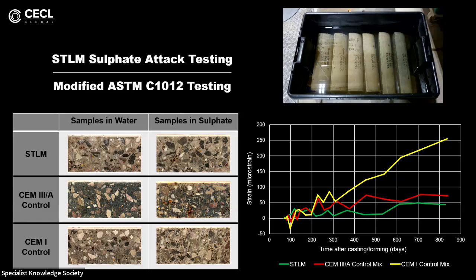Sulfate testing, sulfate attack being a durability concern in certain geological environments. We've done modified ASTM C1012 testing, where we've submerged samples in a strong sodium sulfate solution and looked at their length change and measured this over time. We've been doing this for over 800 days now and have seen very low expansion from the STLM samples in our monitoring to date, and it compares very favorably to control concrete samples, and visually as well. You can see in the bottom left there, the control samples are showing visible signs of distress, whereas the STLM samples are remaining almost as good as when they went in.